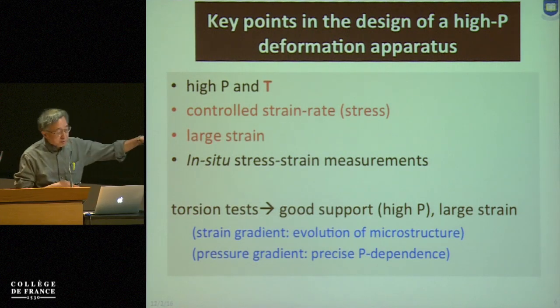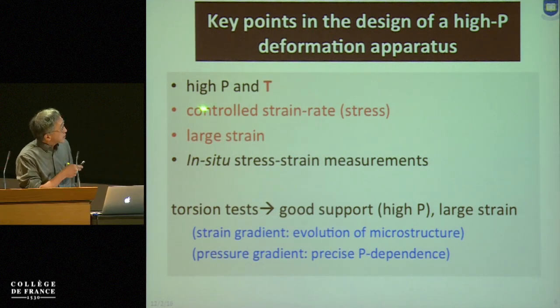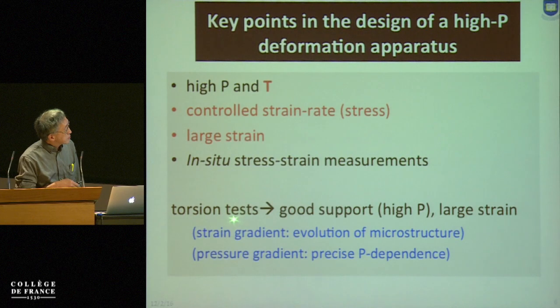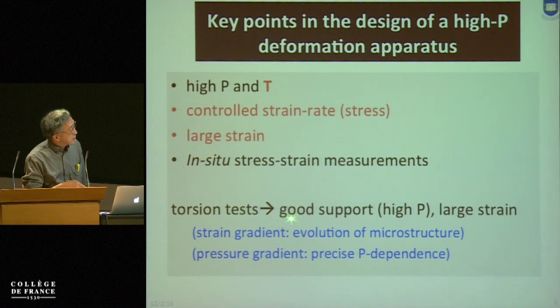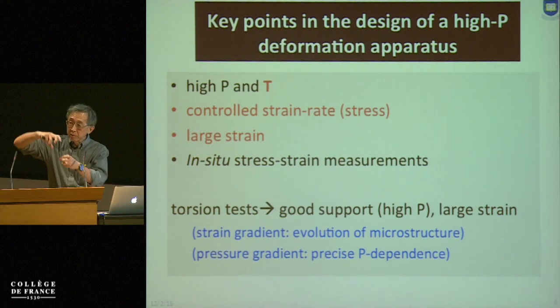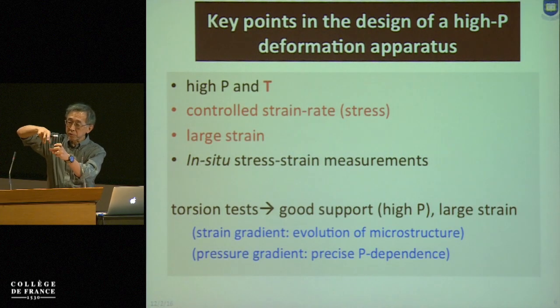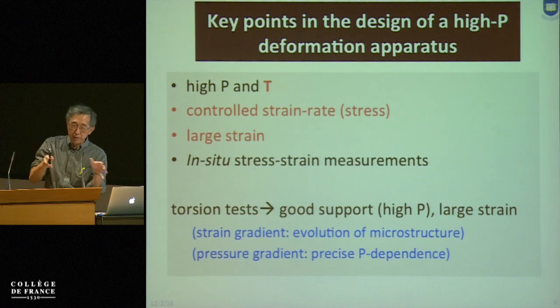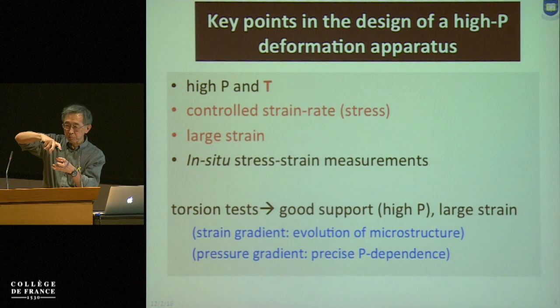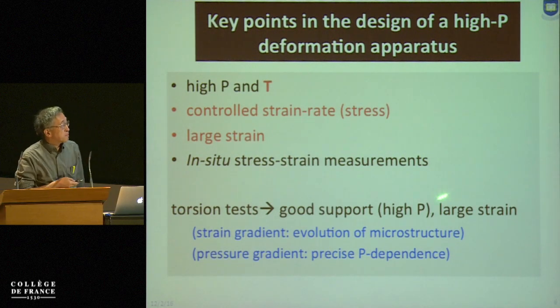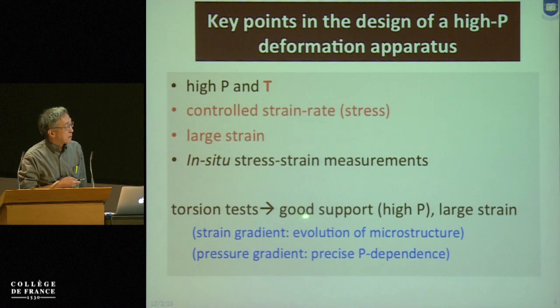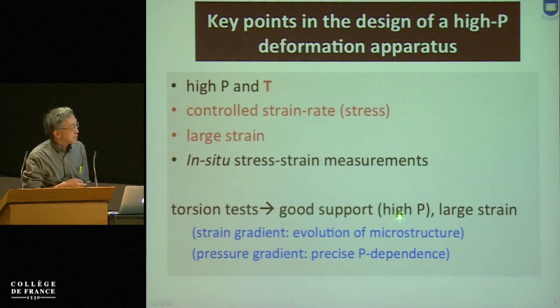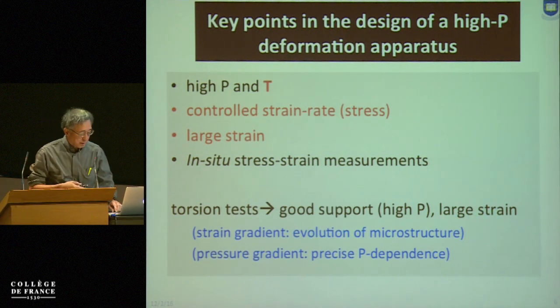So to satisfy those conditions, I chose a torsion test. As I said earlier, it gives good support for high pressure. You just rotate, so the geometry of supporting the anvils with some material doesn't change when you rotate. So this is good, secure support to go to higher pressure, and it could go to large strain.